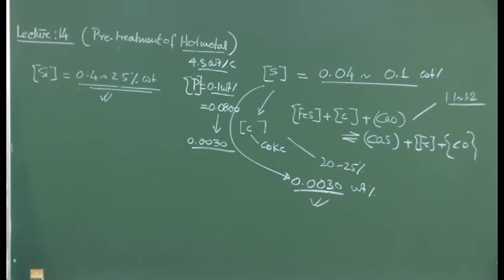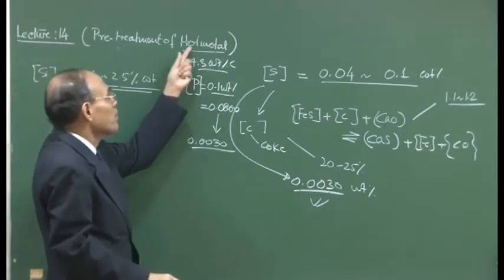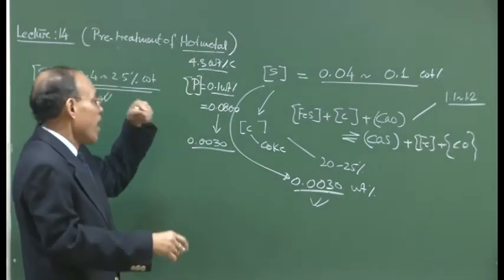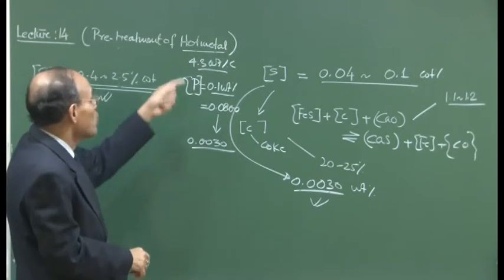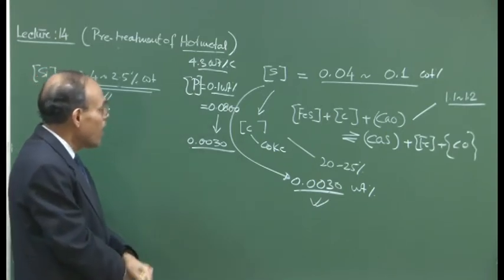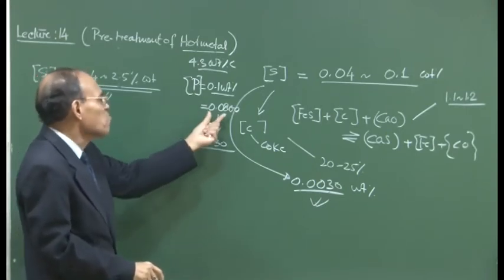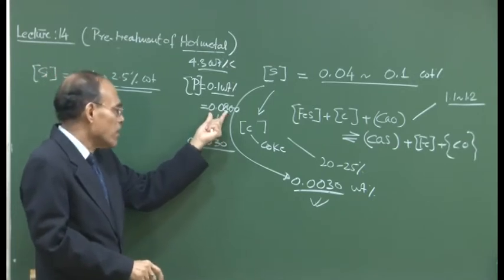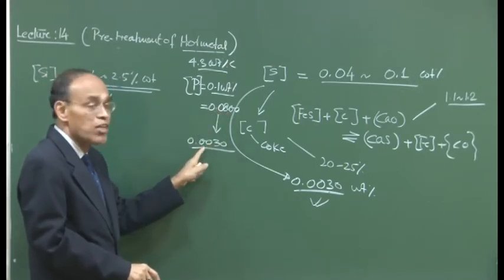And phosphorus and sulfur, as you all know, are detrimental to the mechanical properties of steel. So we would like to... A range of phosphorus can be present in the hot metal. The higher the phosphorus content of the ore, the more phosphorus there is going to be in the hot metal. And if you have this much phosphorus, more or less typically present in hot metal, then you have to refine it to bring it down.